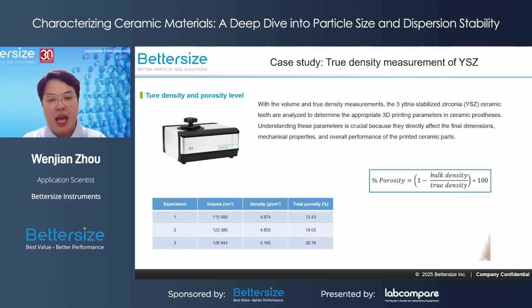Samples with a porosity level between 10 and 15% are generally considered good. We measured 3 samples, and sample 1 performed better than samples 2 and 3 because it has the lowest porosity level.